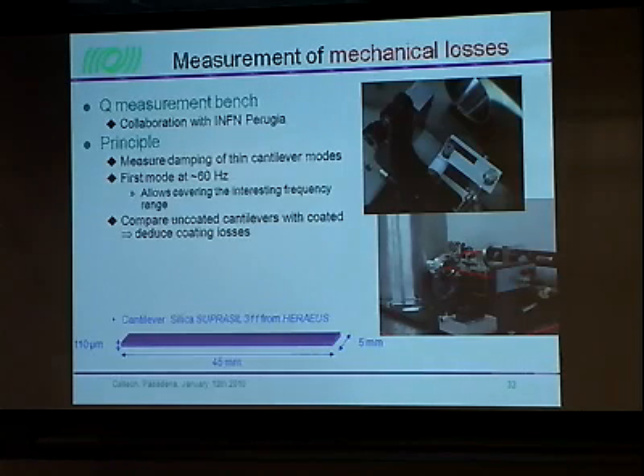The other instrument is the one which allows measuring the mechanical losses. This is based on cantilever springs, thin cantilevers made of silica, which are clamped at one end. You measure the Q of the cantilever before the coating is deposited, then you measure it again once the coating is deposited. You compare the two measurements and you deduce the losses in the coating.